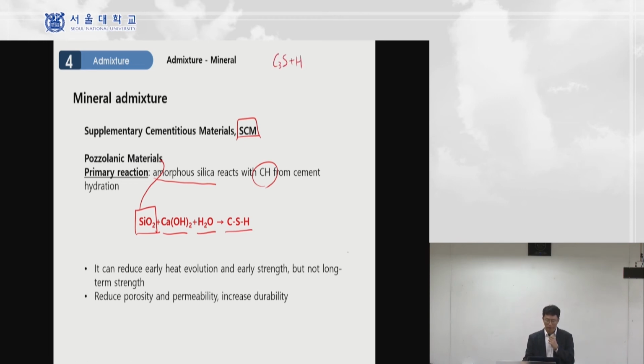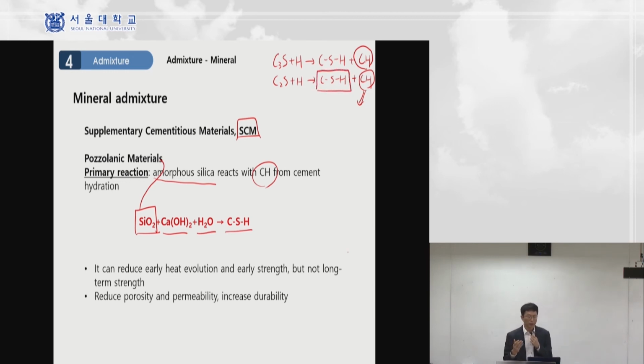C3S plus water will produce CSH plus CH, right? C2S plus water will also produce CSH plus calcium hydroxide. So this calcium hydroxide, you will see later, is a very, very important component from the chemistry perspective. Like we learned previously, this calcium silicate hydrate is the most important component in terms of strength. Without calcium silicate hydrate, it does not have binding property, binding sand or gravel, to have some strength from the composite material. So having more calcium silicate hydrate, we can expect a higher strength.